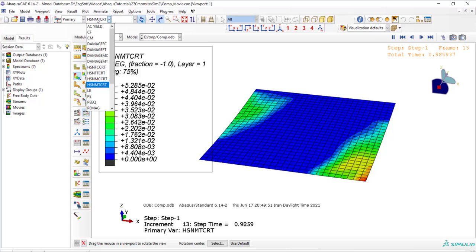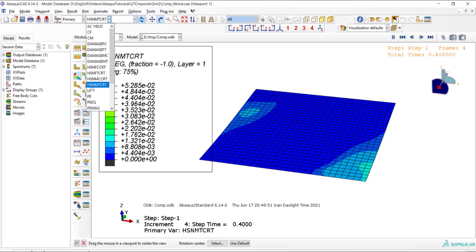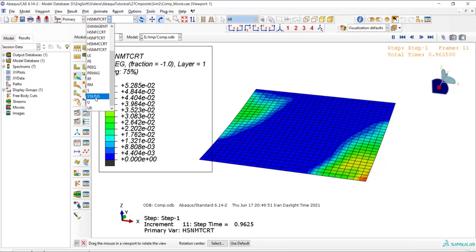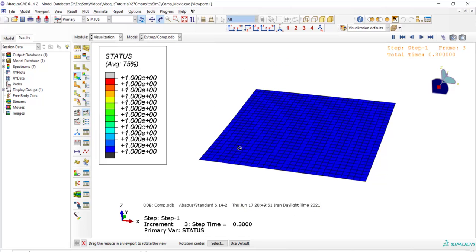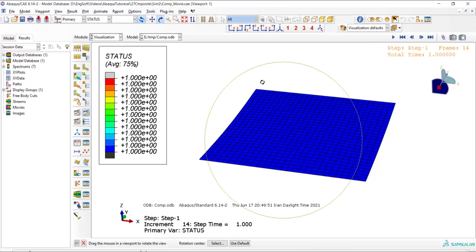Finally we pull out the status of elements. And you can see that the status is 1 for all elements. Please notice that only if in an element in all section points all modes of damage are active, this element will be deleted and the status will be 1.